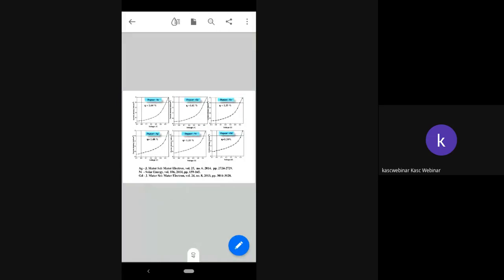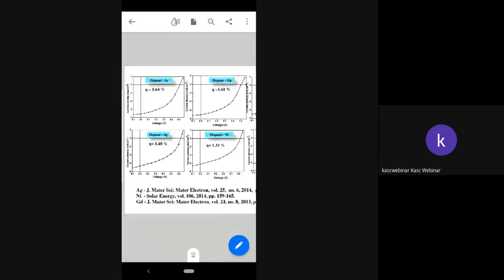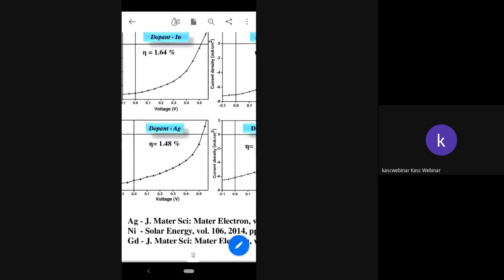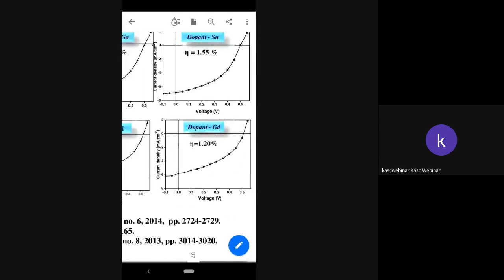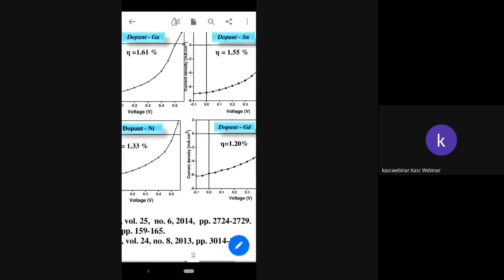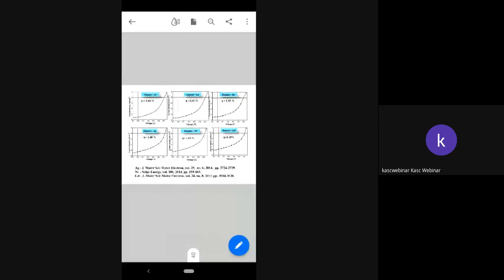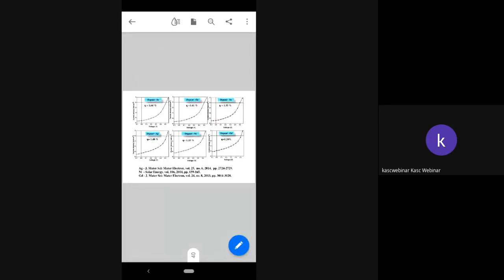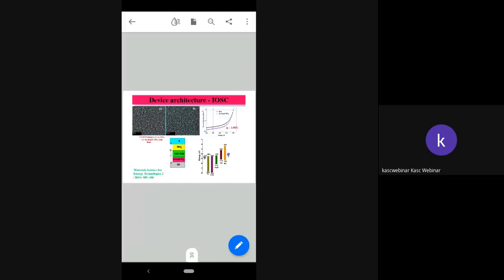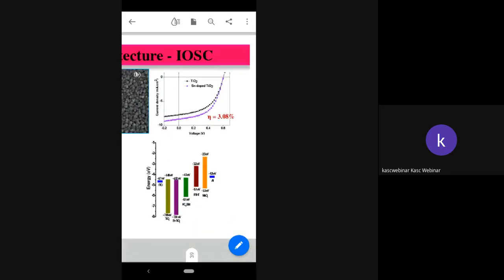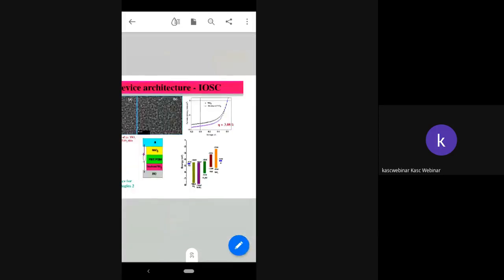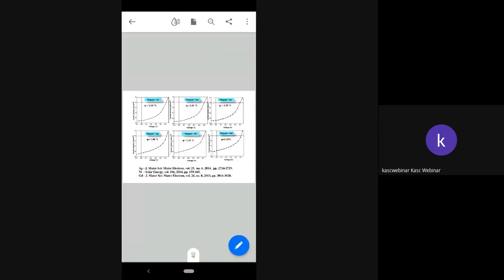And moving on to the next slide, this graph shows the JV characteristics of different dopants into TiO2. The first one corresponds to indium, second gallium, third tin, fourth silver, fifth nickel, and sixth one gadolinium. This efficiency we have obtained for normal quantum dot sensitized solar cell by using this type of dopants. But you can see the efficiency is comparatively low when compared to the previous case, inverted organic solar cell. Here also we have used the tin dopant, but the efficiency is comparatively high. This is because of the change in device architecture.